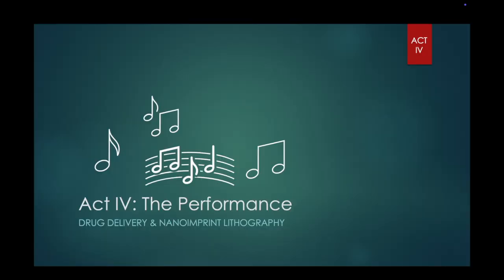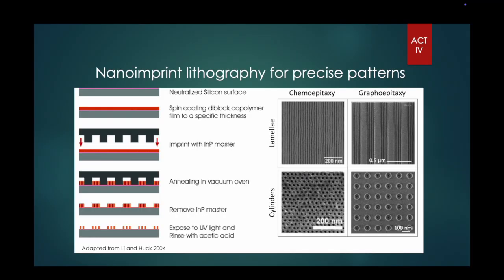The two main applications of block copolymer self-assembly I'd like to talk about today are for nanoimprint lithography and drug delivery. When high-resolution patterning is needed at very low scales, self-assembling block copolymers can be used as templates and scaffolds for later structures. First, a diblock copolymer is spun onto a substrate, which is then heated and mechanically imprinted, hence the imprint part, to induce self-assembly, with the target morphologies of cylinders and lamellae in specific regions on the substrate. To ensure proper spacing and a defect-free system, self-assembly is often aided by chemical or topographical pre-patterns, chemo and graphoepitaxy. Self-assembly can also be guided, though, as we discussed, with an external electric field.